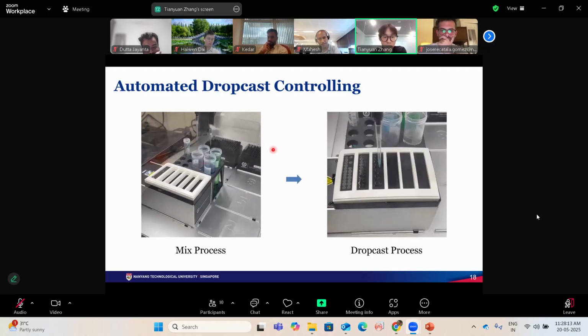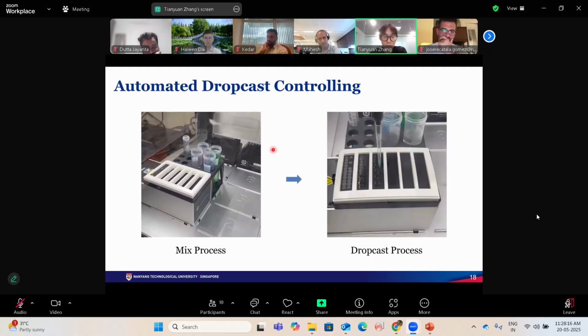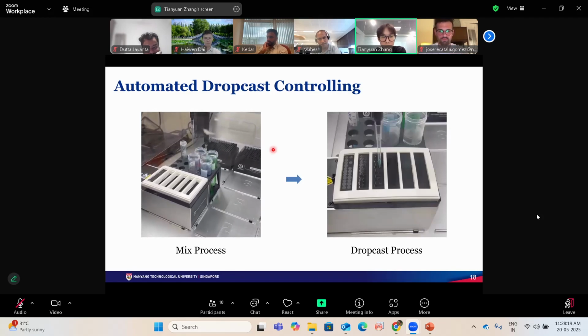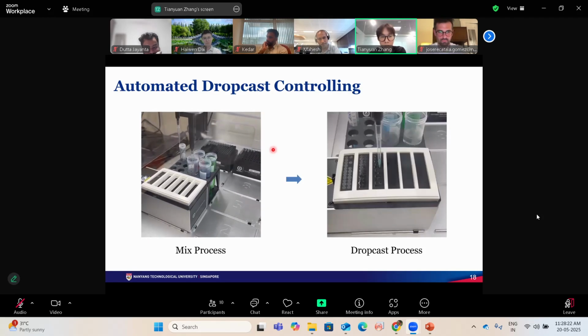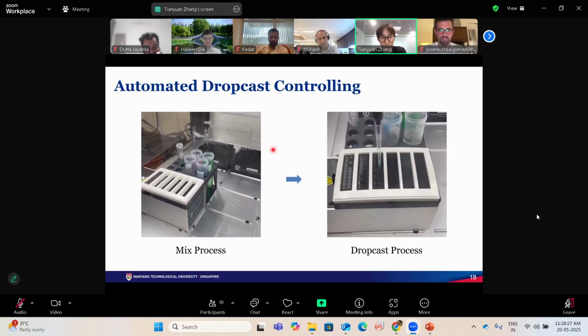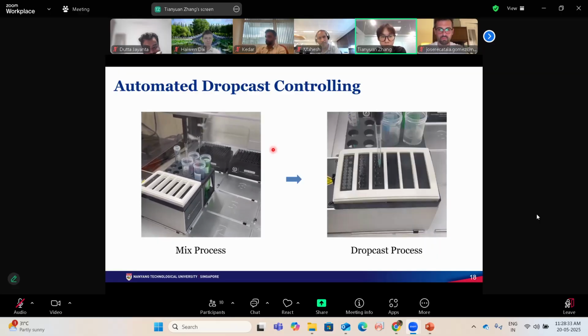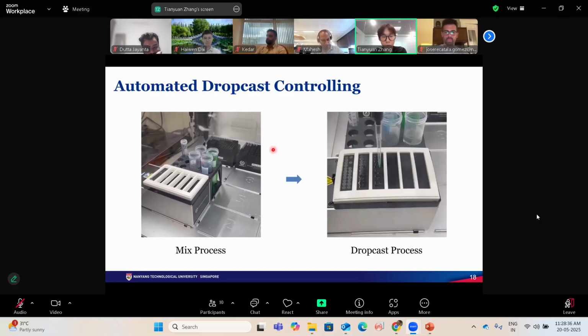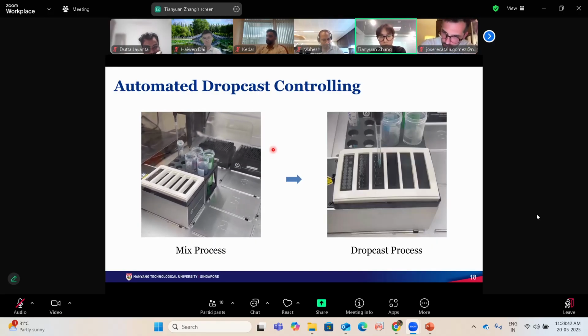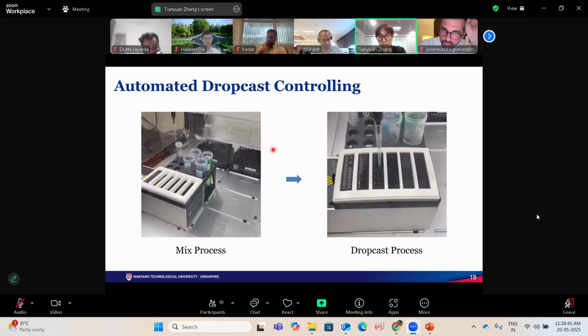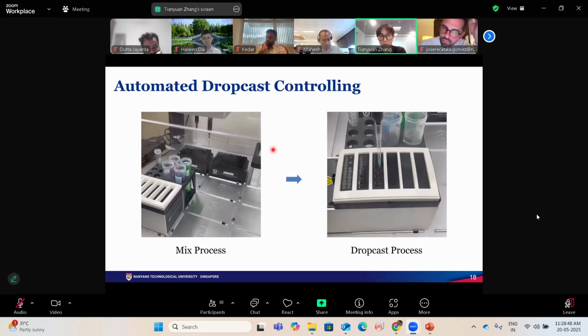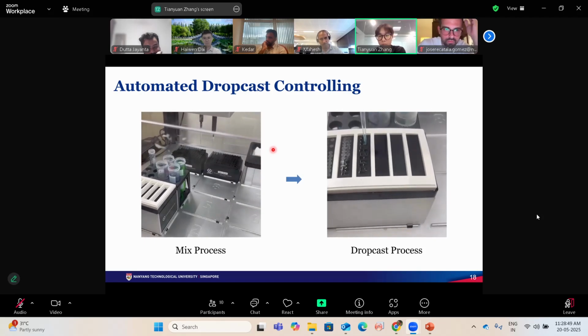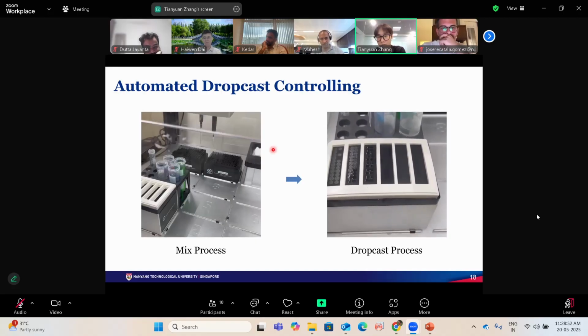First is the mix process. We will use the tip to absorb 18 microliters of nickel or silver salt at first, and then absorb 162 microliters of the copper salt and mix them in a new tube. The process will repeat 30 times to satisfy the need that we want to synthesize 6 samples at one time. And after it is mixed well, we start our dropcast processing.